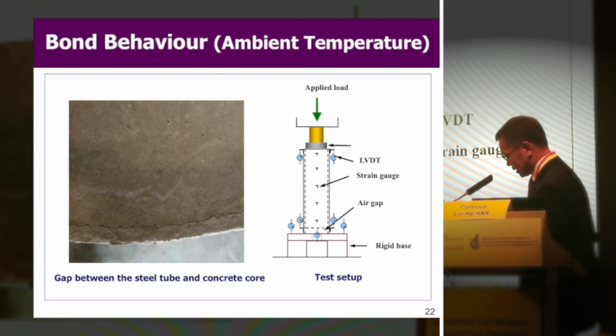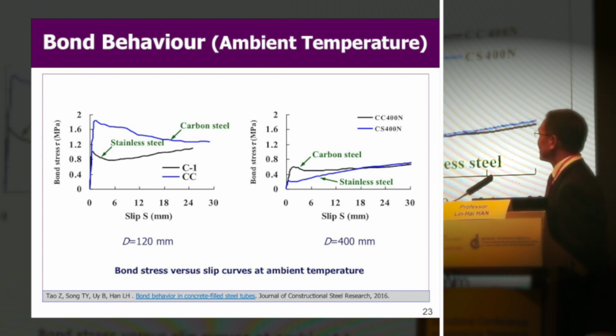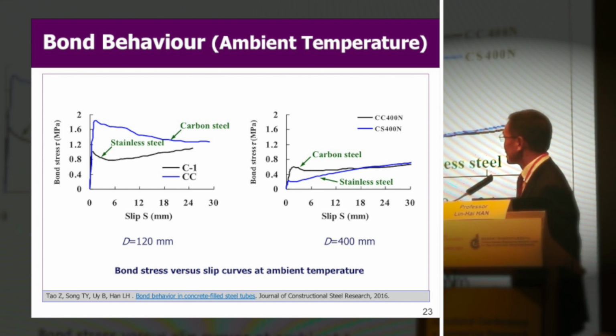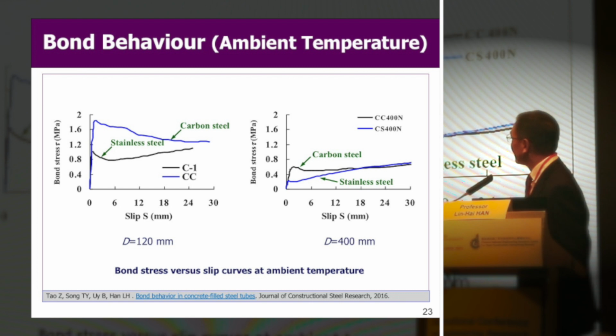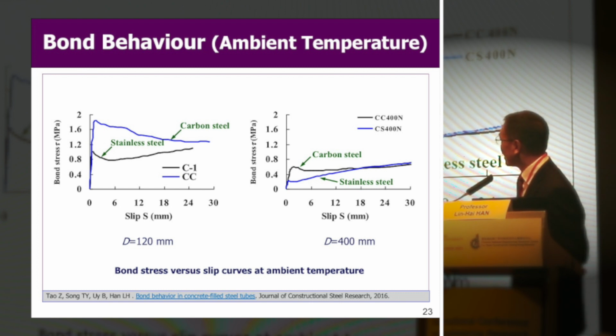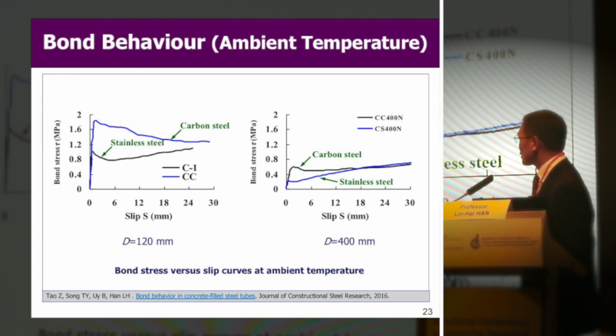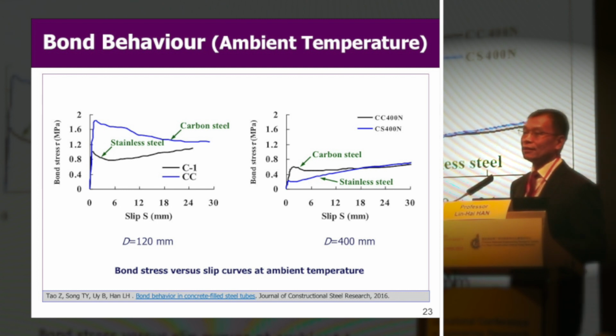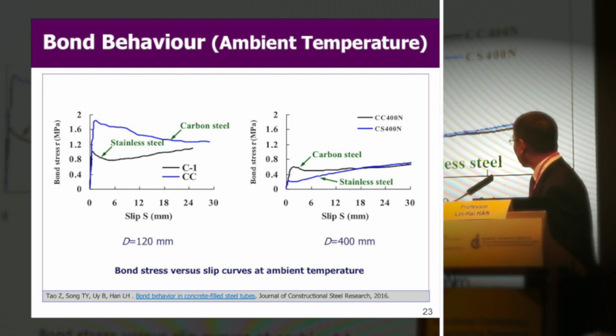Some of the test results: you can see the full response of the bond strength and slippage curves. Again, for the carbon steel tube, it goes like this. For the stainless steel tube, it goes this way. This is for the circular section, with a diameter of 120 millimeters. For the larger section, you can see the lower bond strength. The larger the cross section, the lower the bond strength. You can see carbon steel goes this way, but for stainless steel it goes like this.